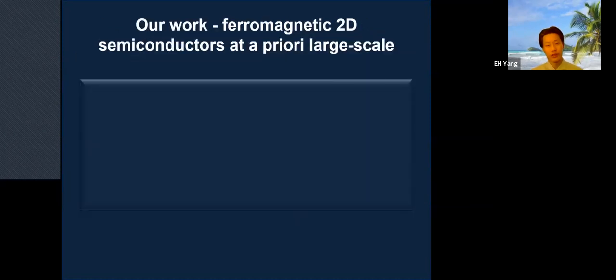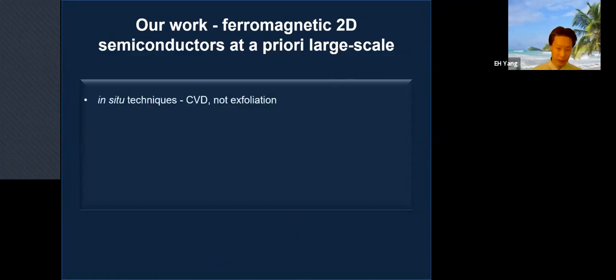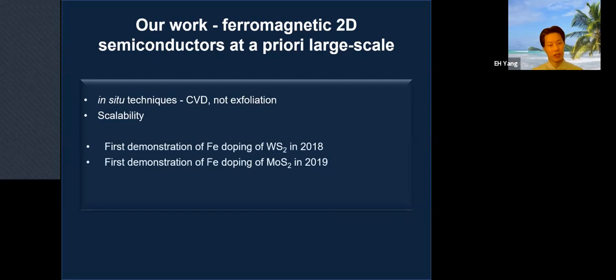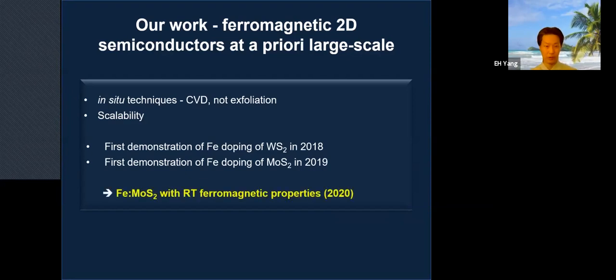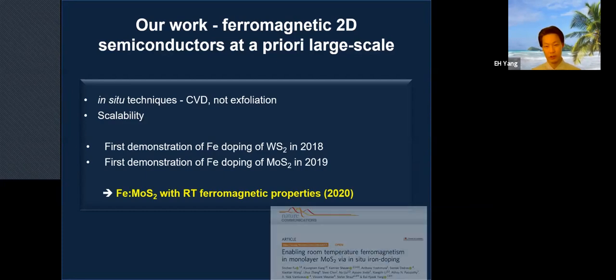Now, what we do here is the synthesis of ferromagnetic 2D semiconductors at a priori large scale. So we use an in situ technique, CVD, and it provides scalability. The first demonstration of iron doping of tungsten disulfide was done in 2018. And then another iron doping of molybdenum sulfide was done last year. We ended up publishing last year's work first because we discovered the room temperature ferromagnetic properties, recently published in Nature Communications.